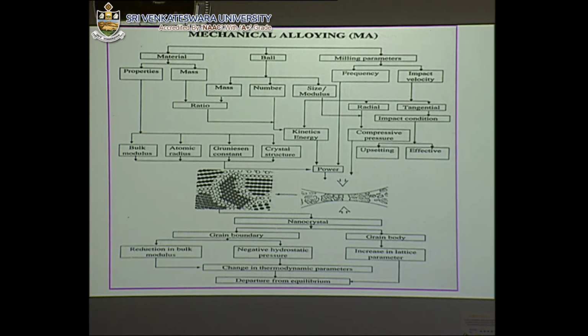This is half MV square, so it depends on the mass. The velocity is 300 RPM. Whichever material has higher density, the impact energy transferred to the powder will be more. So half MV square. We are using the tungsten carbide ball, whose density is more than steel, and therefore the formation of nanoparticles is higher in the case of tungsten carbide.